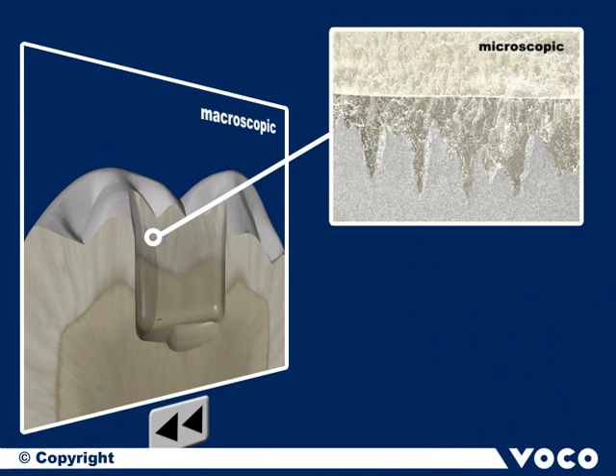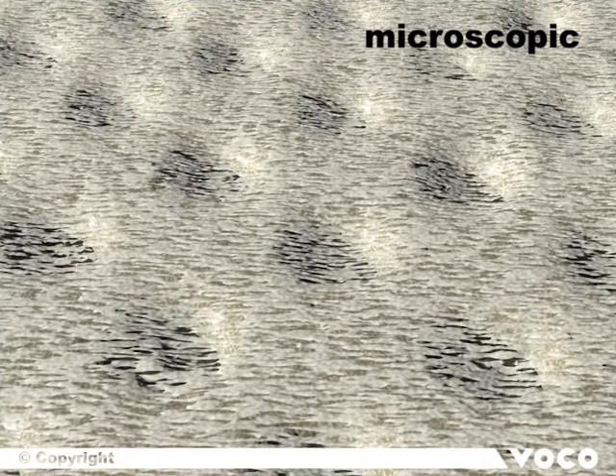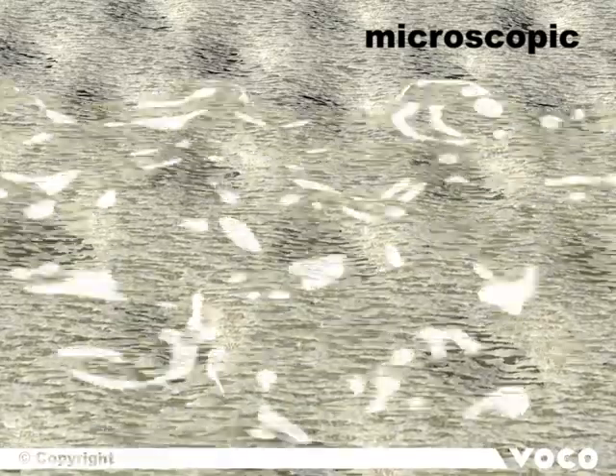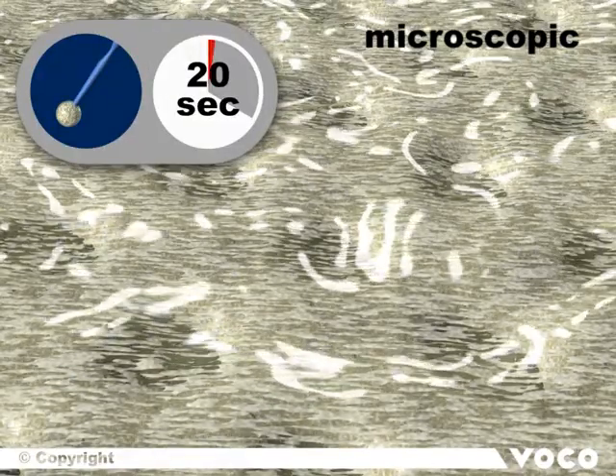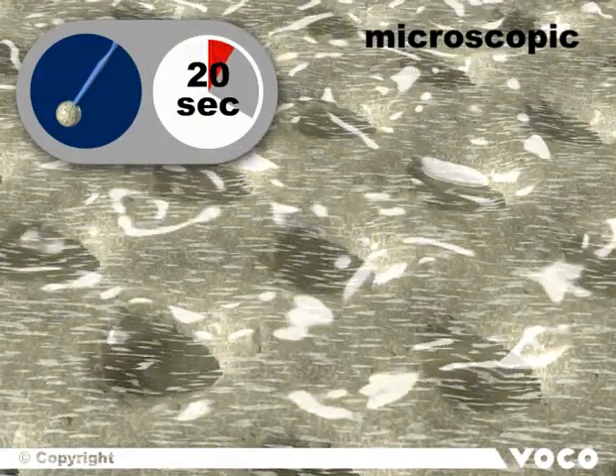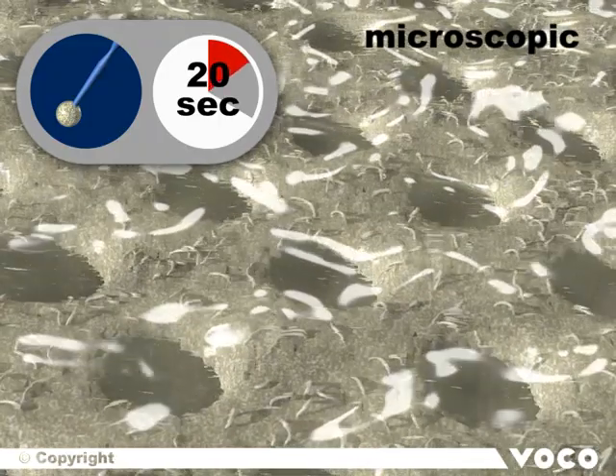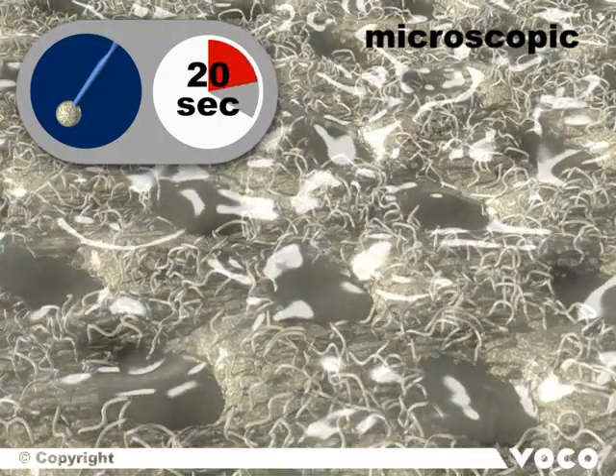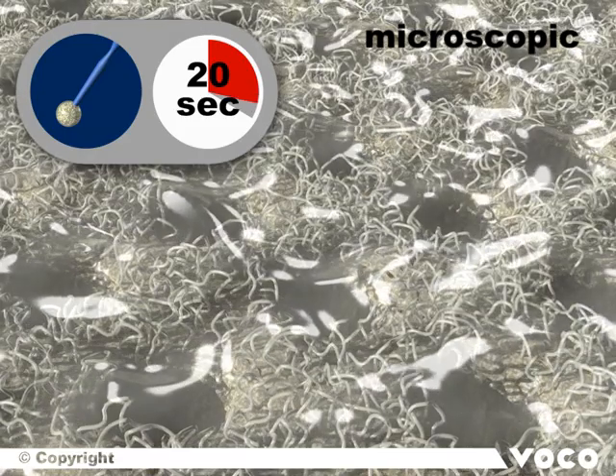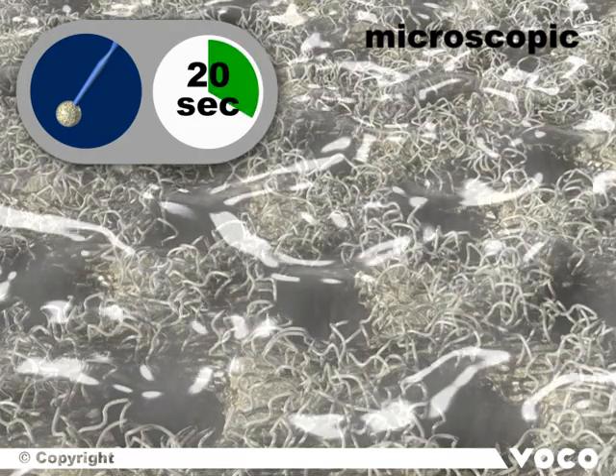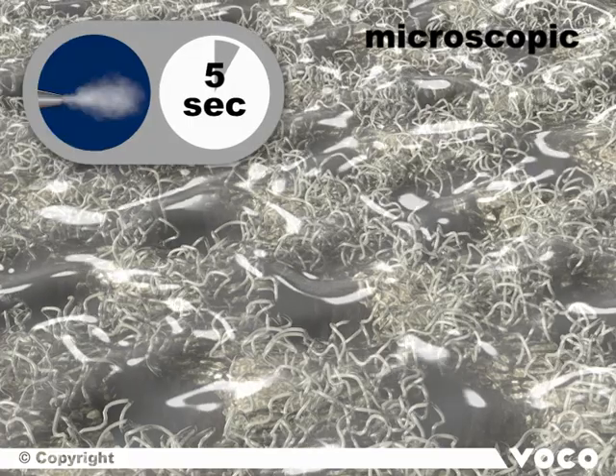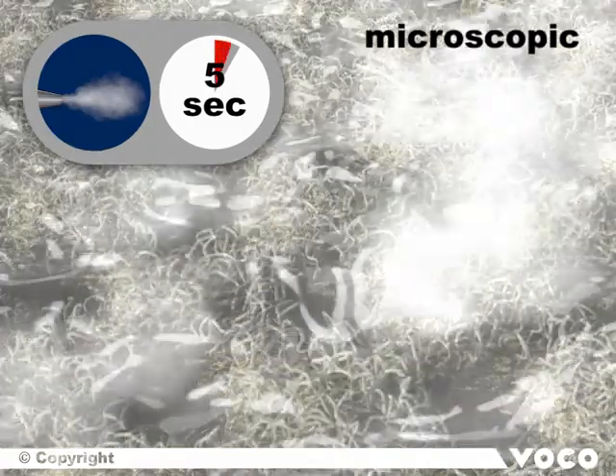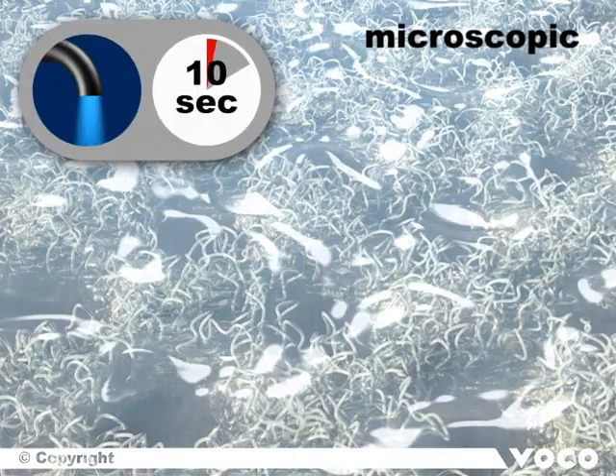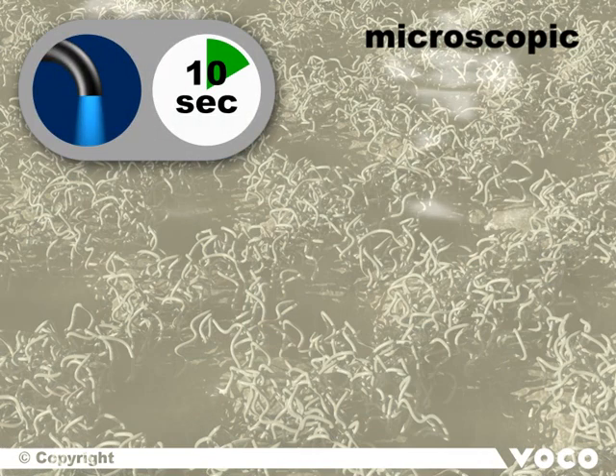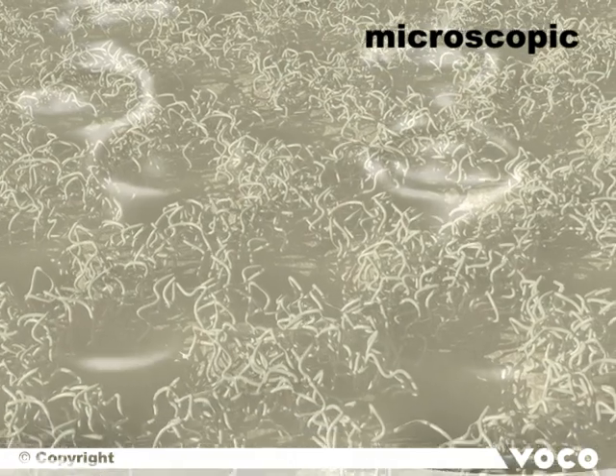The wetting of the dentine with the universal adhesive used in self-etch mode leads to some more complex reactions compared to enamel. During the initial acidic phase of the adhesive, the calcium on the outer surface of the tooth substance is dissolved. The dentine tubules are opened and the collagen fibers are exposed. The newly formed hybrid layer is now fixed by the gentle air drying of the solvent and light curing. Dentine tubules are reliably sealed by the adhesive which has penetrated them, creating tags.